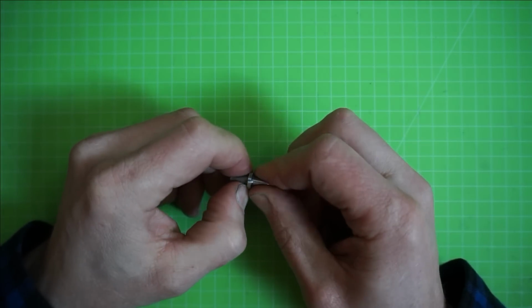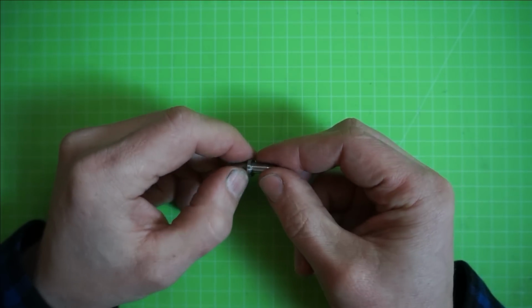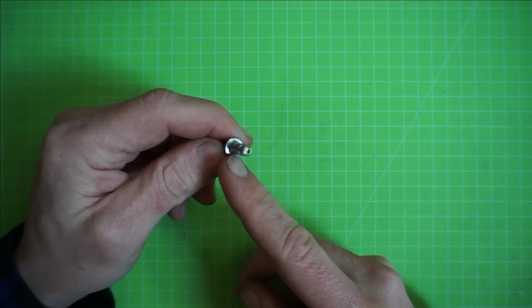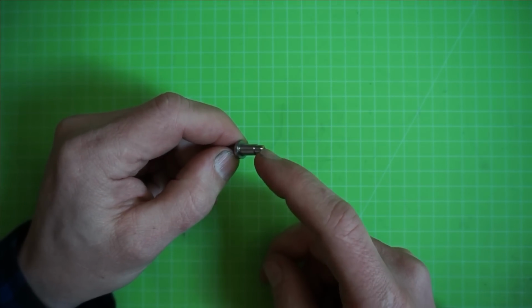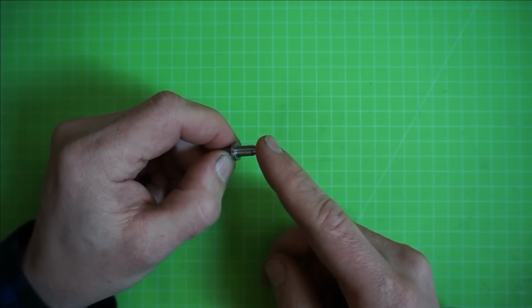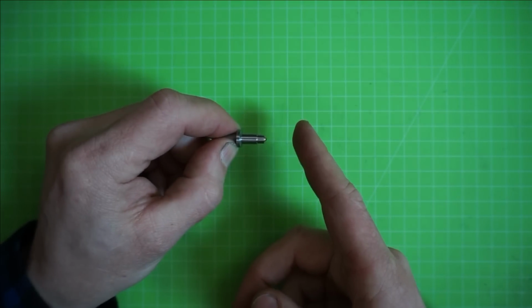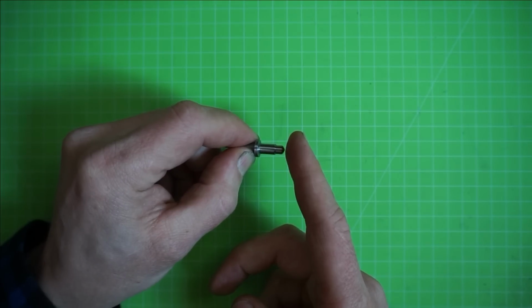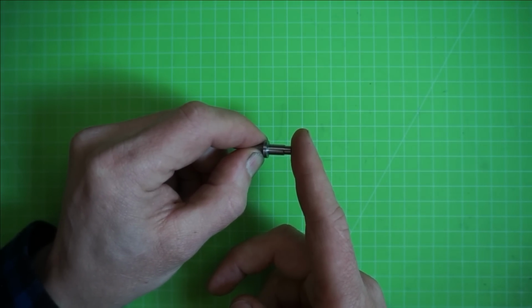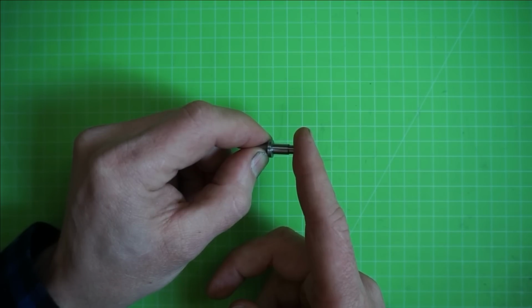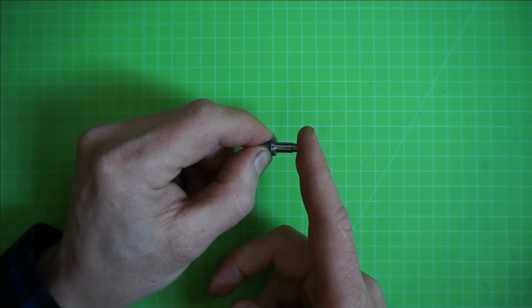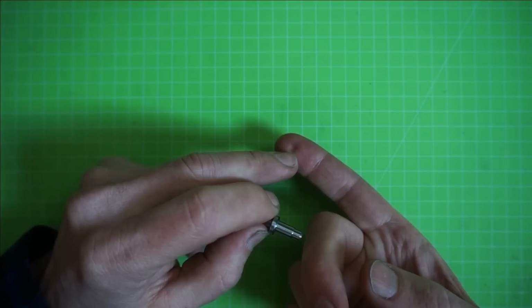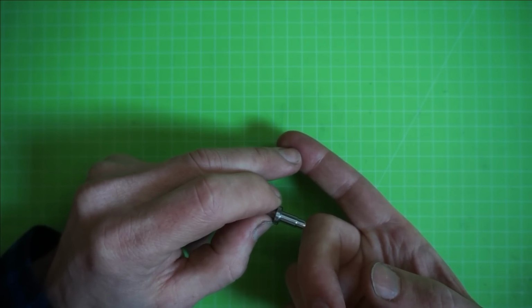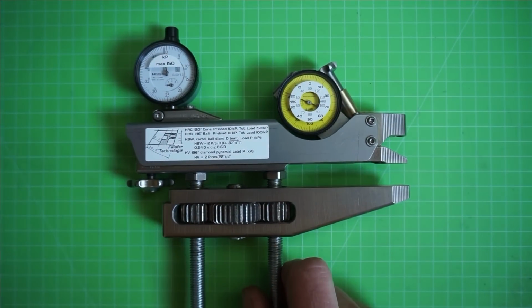With all hardness testing definitions, there is a certain similarity. These methods require an indenter, which may look like this one and which may have a tip shape, or it may be a cone, a pyramid or a ball. It requires that this indenter is forced as perpendicularly as possible into the workpiece or sample surface with a defined force. And then we either measure how deep it sinks into the surface, which is true for the Rockwell methods, or we measure the size of the indent, which is true for the Vickers and the Brinell methods. Now, let's get an overview of the tool and see how this is done here.